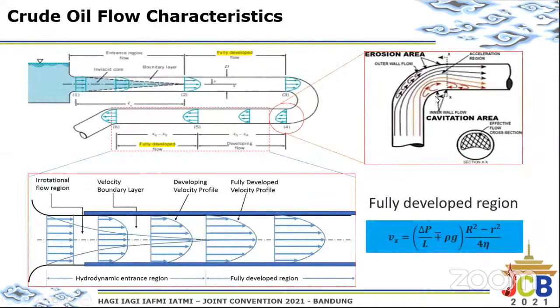This is the illustration for crude oil characteristic. If we use a figure, we can see the detail like this, and in our campus we also make this as a closed flow loop system for testing the flow characteristic and corrosion damage mechanism to line pipe material. We call it the closed flow loop system testing. And this is what we get from the corrosion flow loop testing in our corrosion labs.